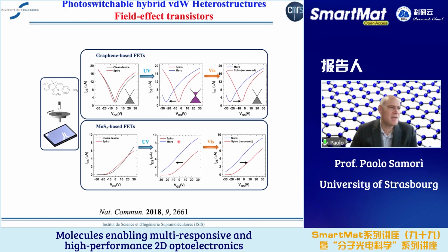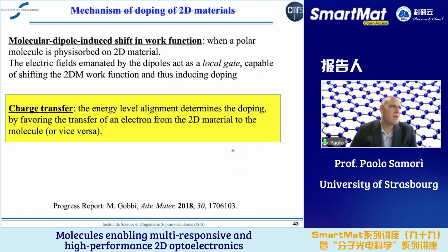Now you can do the very same doping and undoping effect, also using MoS2 as the underneath layer instead of graphene. And you can see the very same process of strong n-doping effect going from spiropyran to merocyanine, and the full recovery with visible light. So that is what you can do by fabricating hybrid heterostructures and using the switchability of the dipoles in spiropyran.